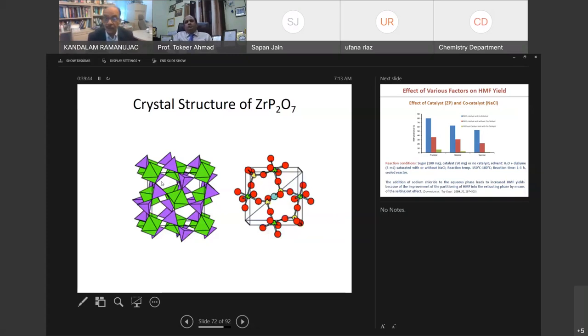Zirconium pyrophosphate is also a very interesting compound in that a lot of compounds expand when you heat them. That's called positive thermal expansion. But zirconium pyrophosphate is just the opposite. When you heat it, it shrinks. So it's a negative thermal expansion material. Although we're not using that part of the equation, we're just using the space to create new lithium or sodium ions, which can be exchanged with protons. So what is the idea here? I have zirconium 4+, which can be a Lewis acid, and phosphorus 5+, which can be a great Lewis acid. And then if I can exchange the lithium with protons in the open structure, I also have a Bronsted acid. So this is how one can take a catalyst, tweak the chemical composition, and create both Bronsted and Lewis type acids.